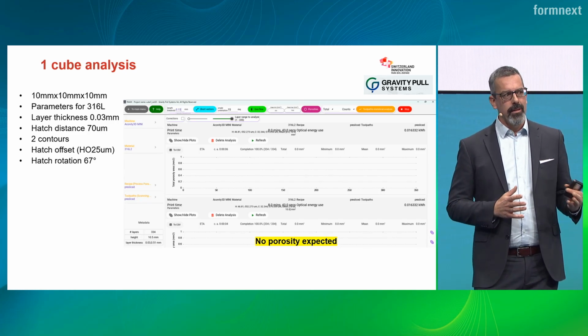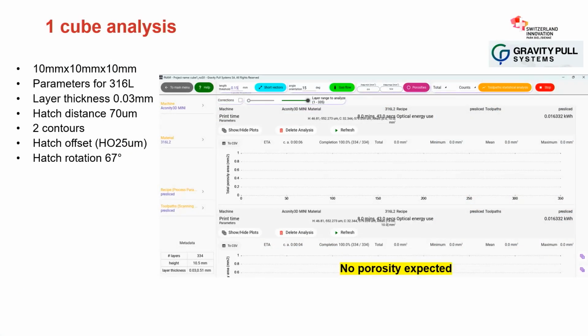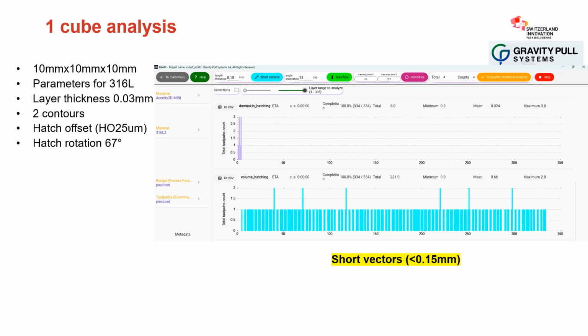Increasing complexity, and you see from when it starts to be really effective. So we start with a cube 10 by 10 by 10 millimeters, printed in 316L using a very well-established, well-known recipe. We have 2 contours, a hatch distance of 70 microns. We have a hatch offset from the contour of 25 micron, and we rotate the hatch by 67 degrees between layers. So we expect no porosity. On the right, you see already a preview of the analyzer that you see in PAM.